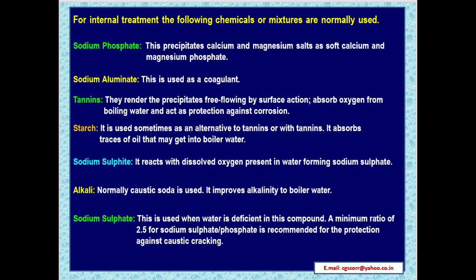Sodium sulphite: it reacts with the dissolved oxygen present in water, forming sodium sulphate. Alkali: normally caustic soda is used. It improves alkalinity of boiler water. Sodium sulphate: it is used when water is deficient in this compound. A minimum ratio of 2.5 for sodium sulphate to phosphate is recommended for protection against caustic cracking.